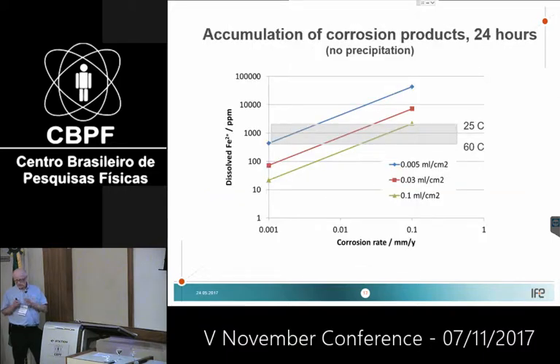And since we have a confined environment, everything happens very quickly. So this is corrosion rate on this axis, and the amount of released corrosion product on this one, assuming no precipitation. And we can see that you reach very high concentration of dissolved corrosion products just after 1 day if you have a reasonably low startup corrosion rate.